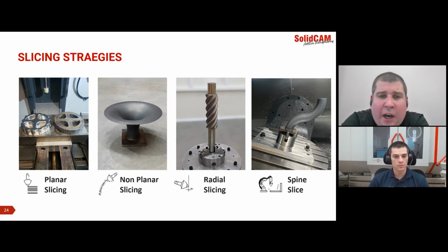Radial slicing, if you're doing a spline or a sprocket type geometry around a shaft, where you're rotating about a certain axis as you're slicing. And then one of my favorite ones is doing a spine slice where you're giving a drive geometry where we're actually changing feed rates to generate a non-linear layer height. So this will allow you to do tubular types of shapes where we're automating the change in feed rate to achieve that curvature.